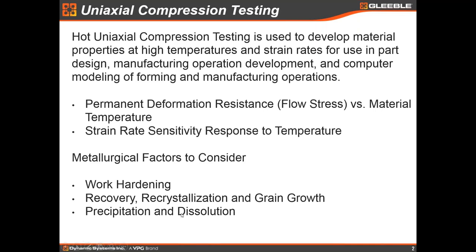Depending on the previous history of the material, you may or may not still have some precipitation and dissolution occurring. That of course is going to be dependent on the heating rate and the hold time at temperature before the uniaxial compression testing, and any changes in temperature during uniaxial compression testing if you have cooling at the edges of a piece of material. You can simulate all that using uniaxial compression testing in the Gleeble.